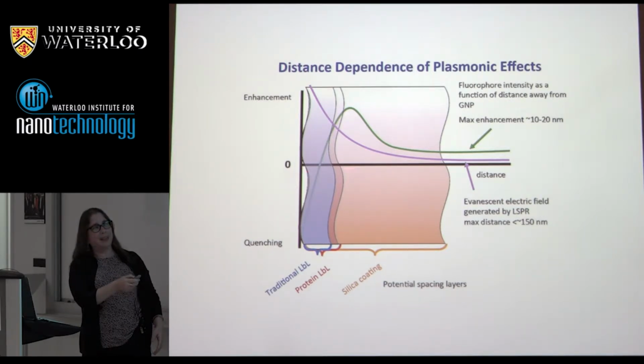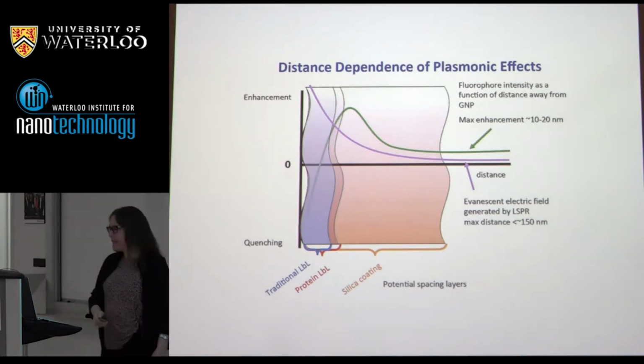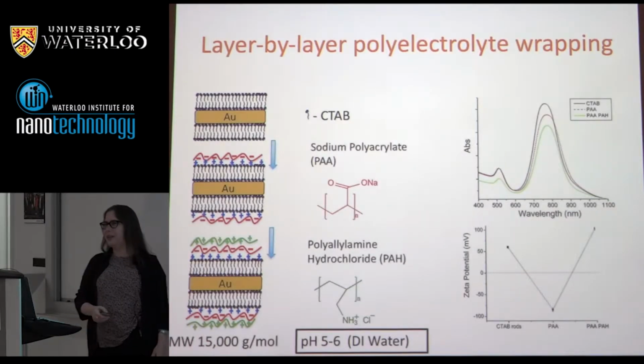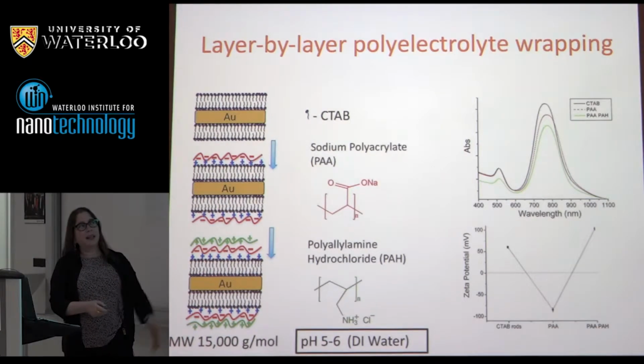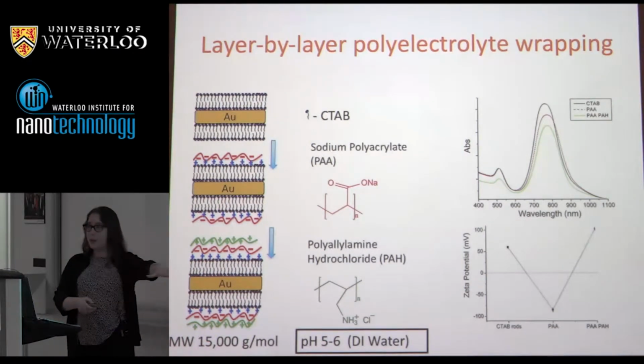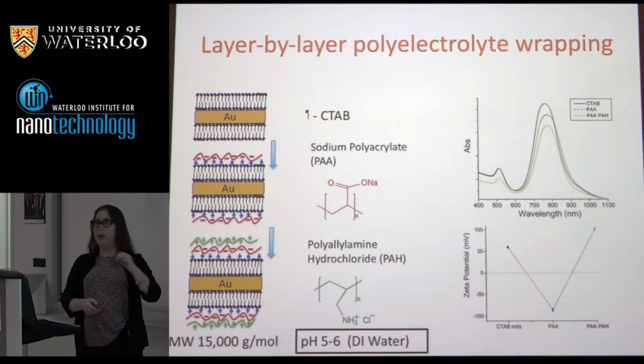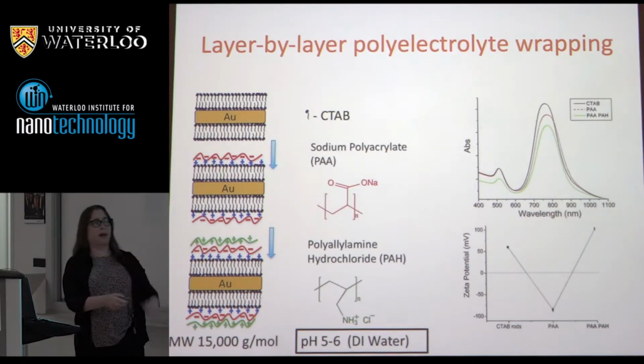Then you've got to think about building layers. If you want to get out 10 or 20 nanometers, what do you do to do that? So one of our favorite techniques for building layers is polyelectrolyte layer-by-layer wrapping. This works great on flat surfaces, and it works well on colloidal particles too. The problem is you have to separate the polymer from the colloidal particle when you're done.